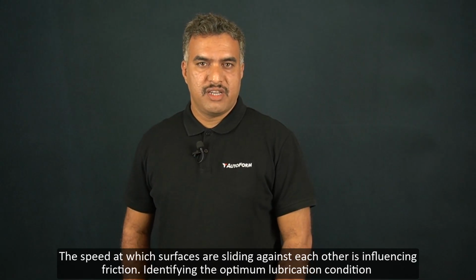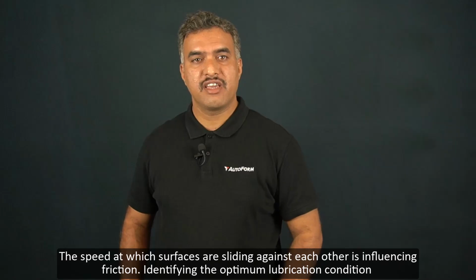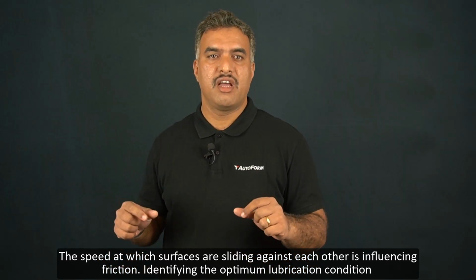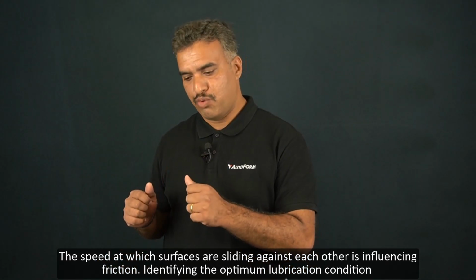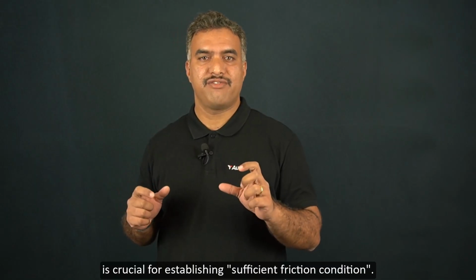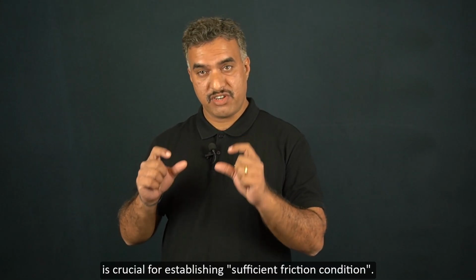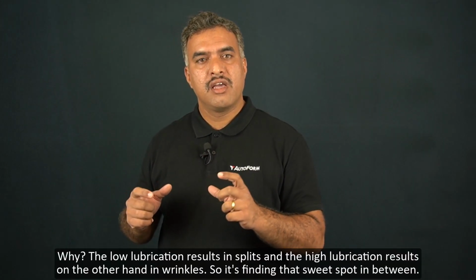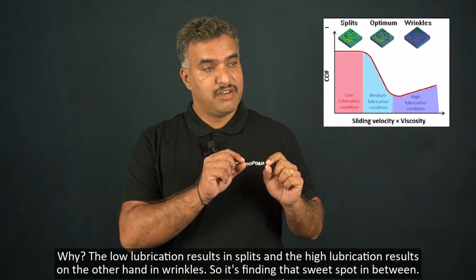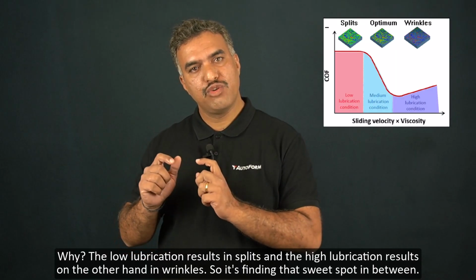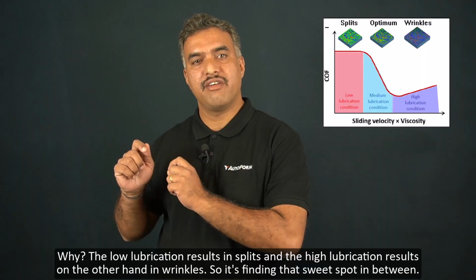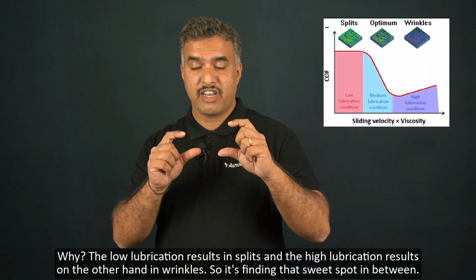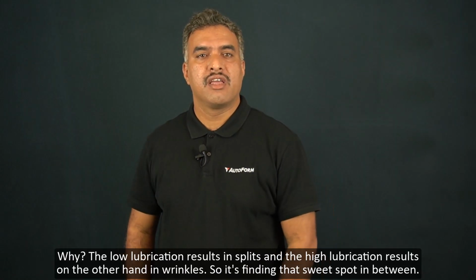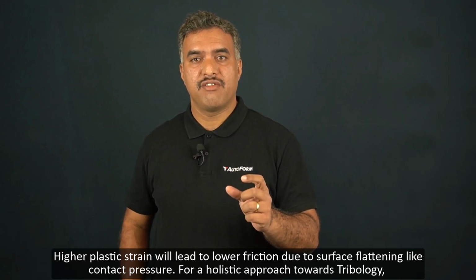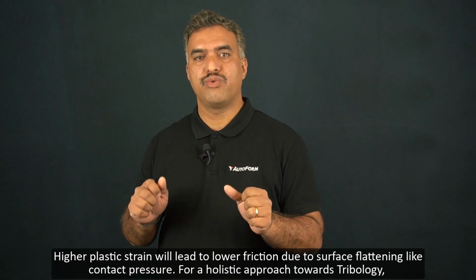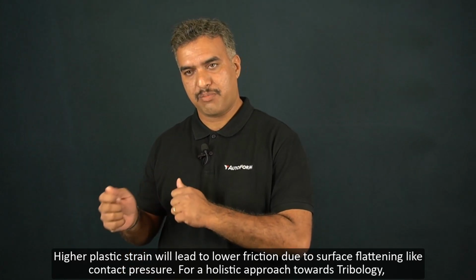The speed at which surfaces slide against each other influences friction. Identifying the optimum lubrication condition is crucial for establishing sufficient friction. Why? Low lubrication results in splits, and high lubrication, on the other hand, results in wrinkles. So it's about finding that sweet spot in between. Higher plastic strain will lead to lower friction due to surface flattening, like contact pressure.